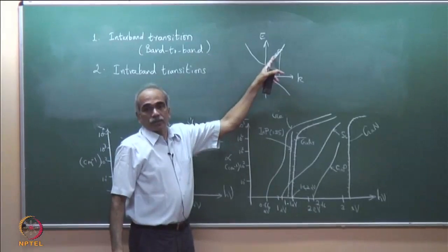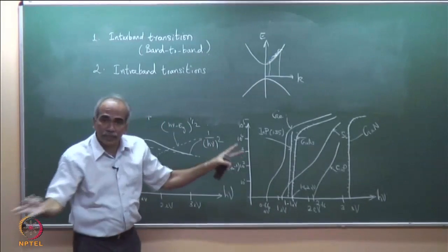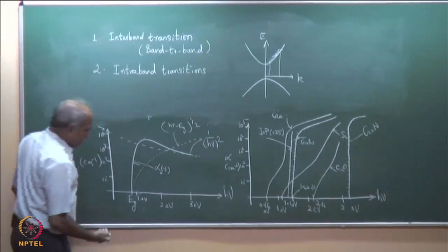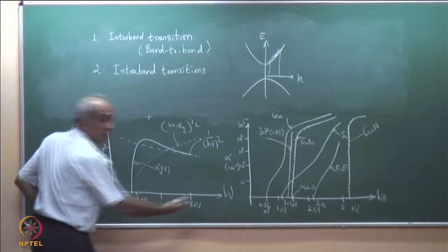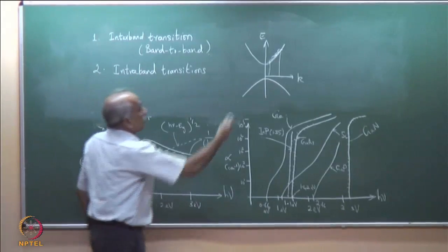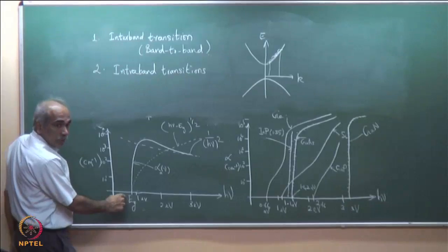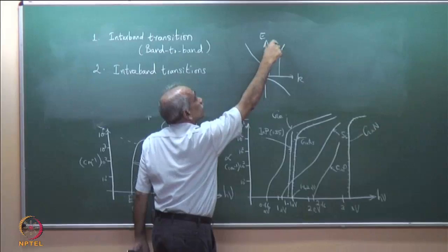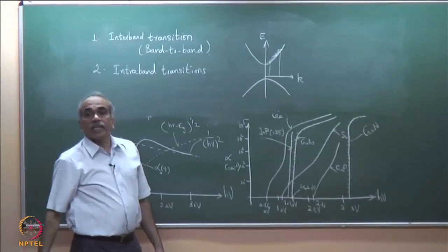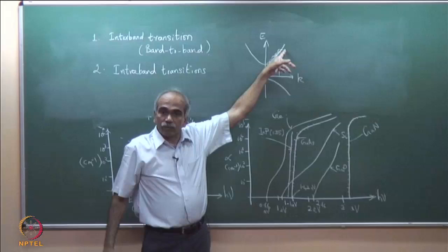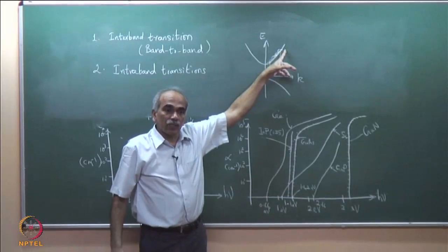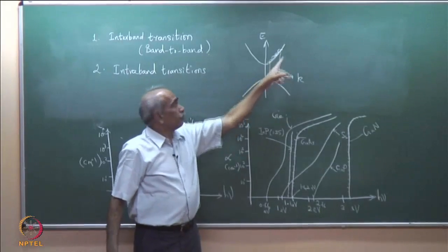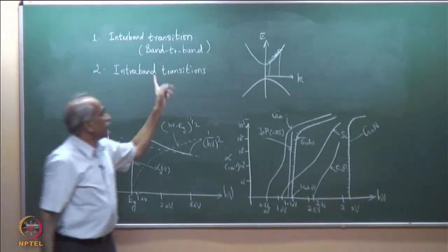This is intraband transition. So, when photons of a broad spectrum of energy are incident, if you assume that the source has all these wavelengths, then some of the wavelengths, particularly here at the lower energy, will result in an electron gaining energy and going to a higher vacant position, and this becomes a hot electron. A higher kinetic energy electron is called a hot electron, but subsequently it will come down by thermalization. This is intraband transition.